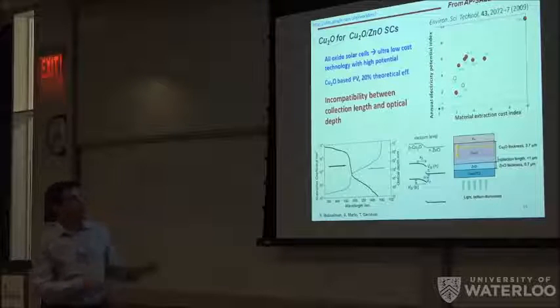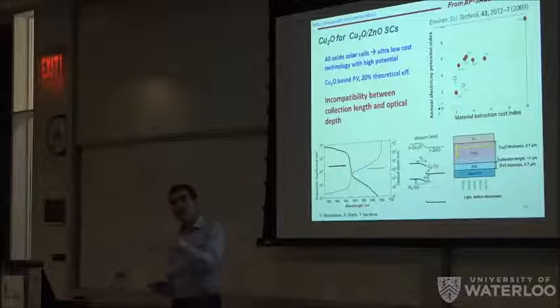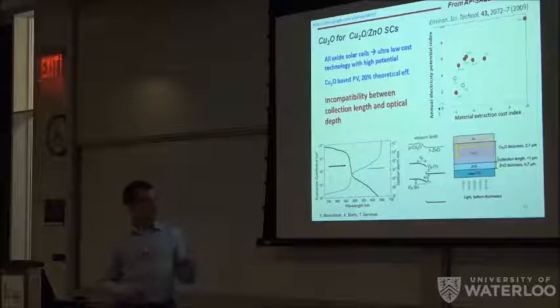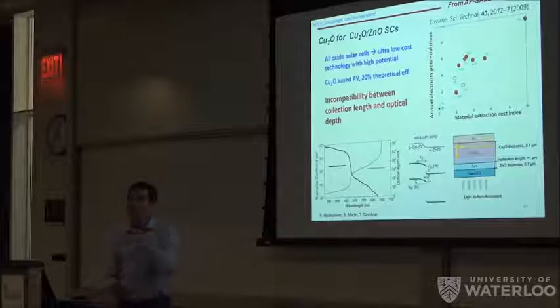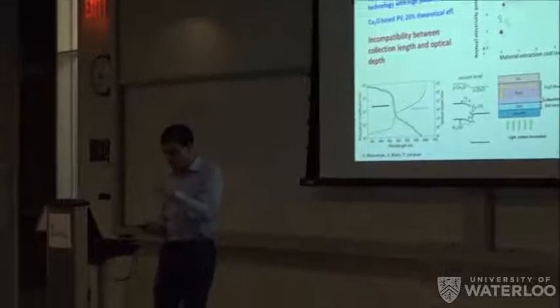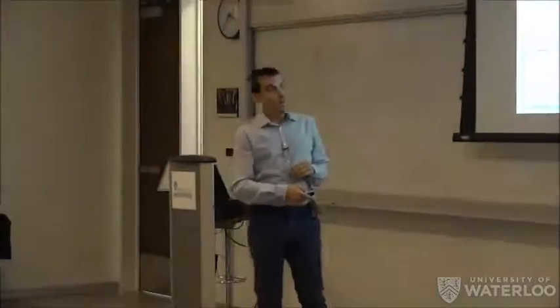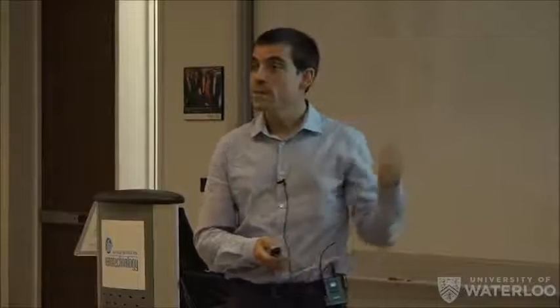And the problem with this system is that we have an incompatibility between the absorption length, the amount of material you need to collect most of the light, the amount of material you need to have a full depletion layer, and, I won't go into the details because I don't have enough time, the thickness you can have to ensure efficient charge collection. And that limits quite badly the efficiency you can get. So what we did, and that's a very nice paper that Kevin published at the time, was to use zinc oxide nanorods to try to maximize this charge extraction. It was even featured on the cover.